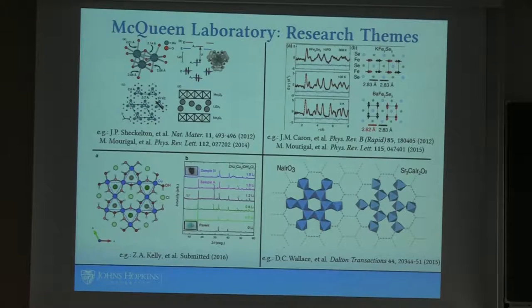Here's something interesting that we figured out in these materials. Here you've got all the d orbitals on the iron that are playing together, but one interesting result that comes out of this is that some of those electrons form magnetic order, but other electrons don't. They actually form bonds between iron atoms. This actually makes sense - it's basically a statement that you have 3d orbitals, and they have radically different bandwidths based on how much they interact between sites. For some of those, the Hubbard U is enough to open up a gap and localize the carriers and make magnetic order, and in other cases not. Since they're one-dimensional materials, presumably you get Peierls-like distortions where you distort the lattice and form bonds.